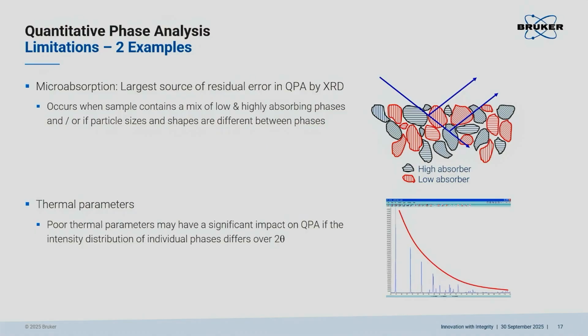It occurs if you have a sample where you have two or more phases with different absorption coefficients. Then you intrinsically run into this error, but it is not generally known. On top of that, you have an issue because of the different grain size and generally a size distribution between phases, which also cause microabsorption problems. So the microabsorption problem is consisting of two effects. First of all, different absorption coefficients of the different phases and different size distributions. I go into the details in a second.